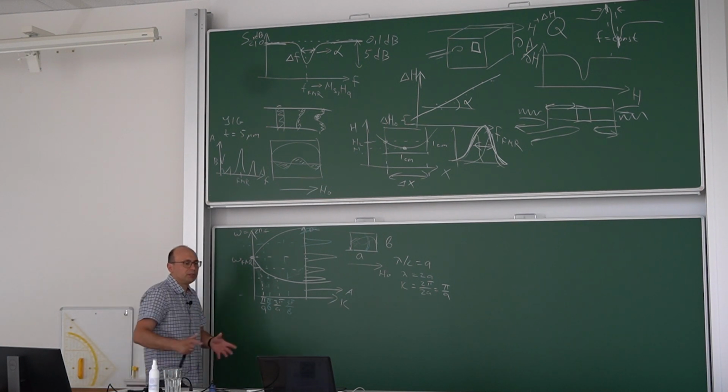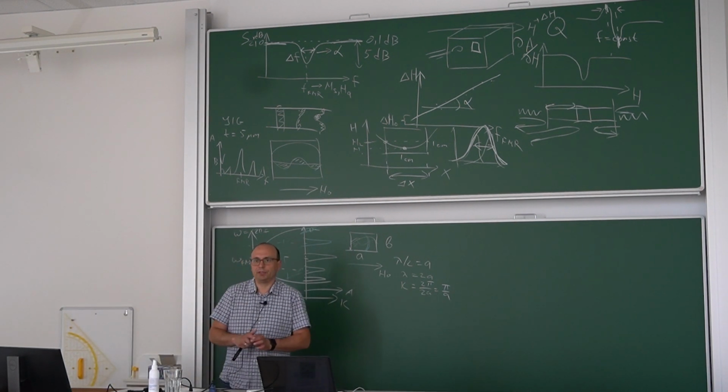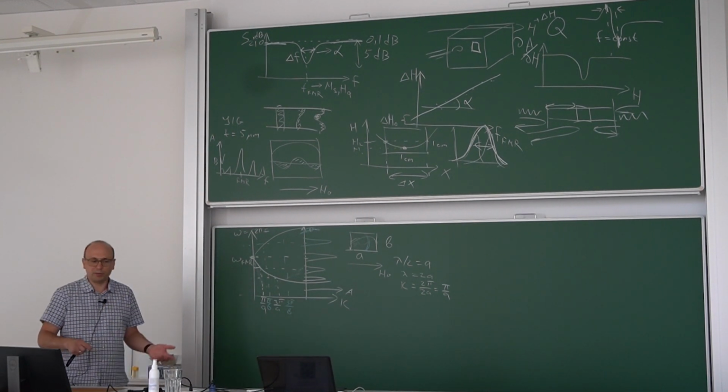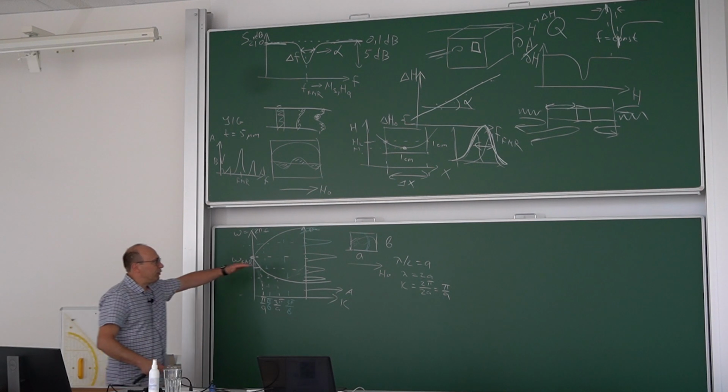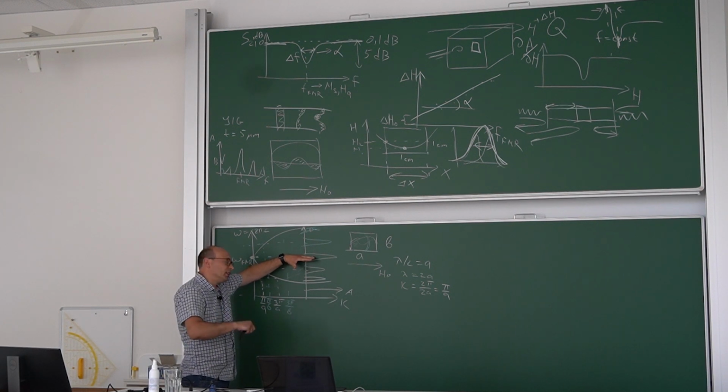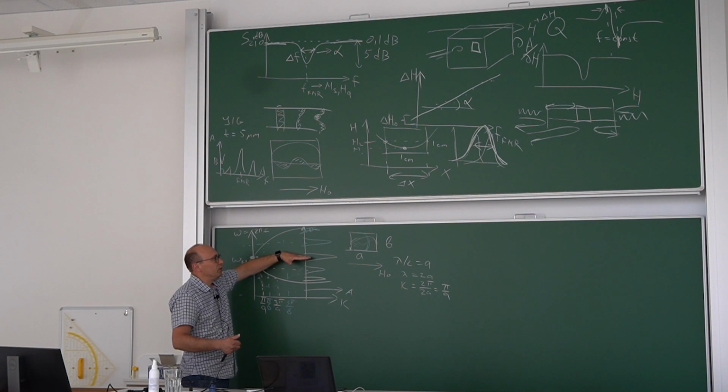From sample to sample, saturation magnetization can be shifted. So ideal for YIG is 1750, but you can have a sample with 1650. Therefore, for the absolute value, usually you need to find a way, whether it's saturation magnetization or anisotropy, to tune it to fit experiment and theory together.